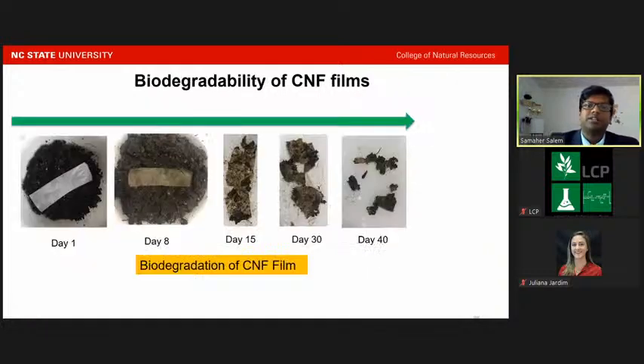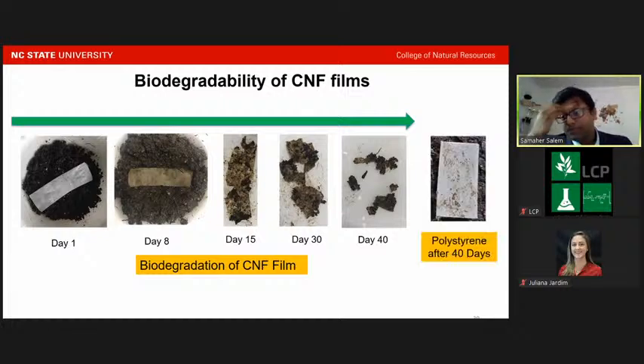Also, we measured the biodegradability of the nanofibrils. So we put the nanofibrils in soil, and we regularly monitored the nanofibrils and how they were degrading or not. And we could say that after 40 days, those nanofibrils were degraded to a great extent, the size of the nanofibril film decreased, and we could clearly see the degradation. However, the polystyrene after 40 days, there was no change actually.